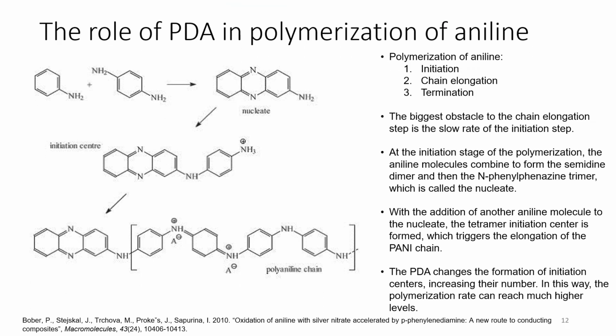The role of phenylenediamine in the polymerization of aniline is very important for the chain elongation process. The phenylenediamine changes the formation of initiation centers and increases their numbers, and in this way the polymerization rate can reach much higher levels.